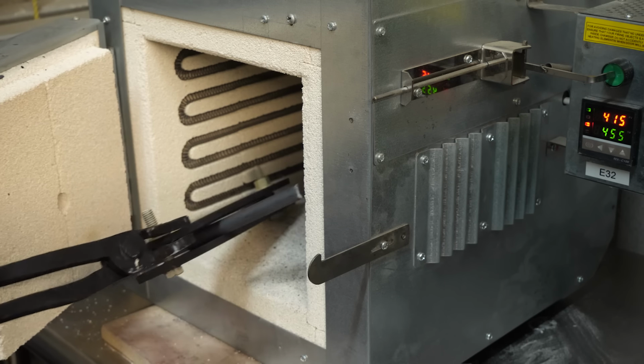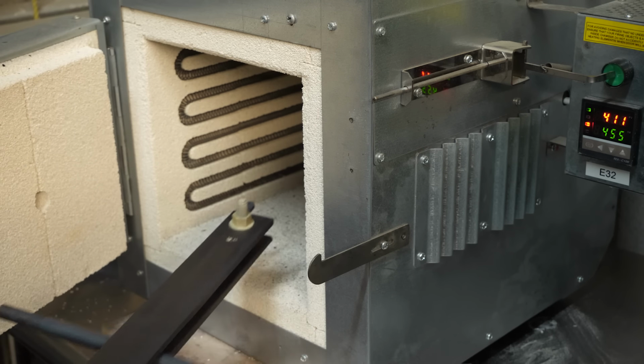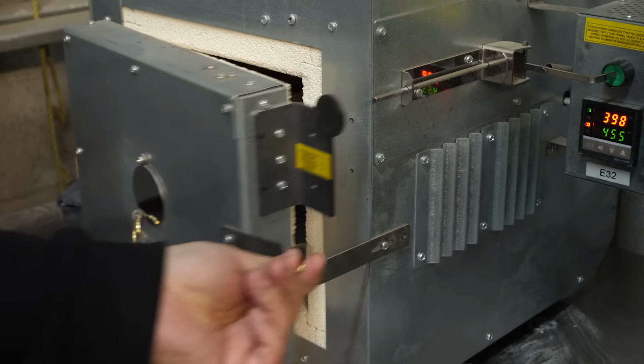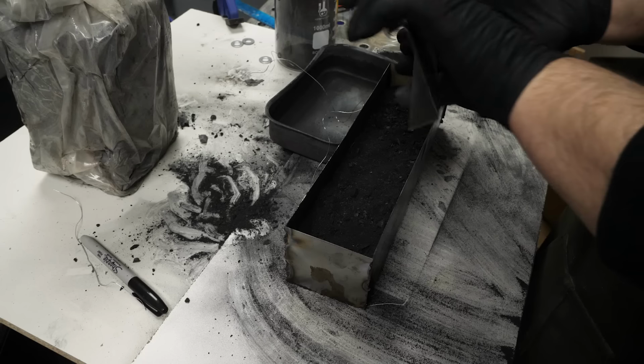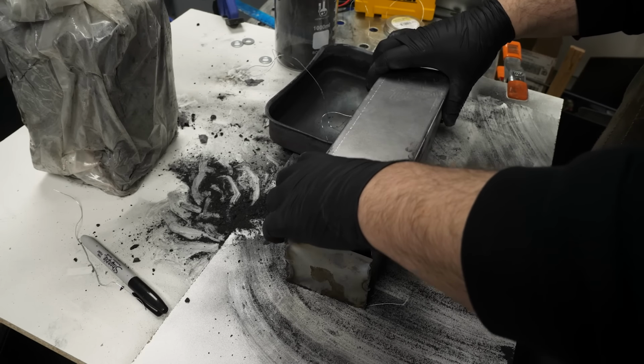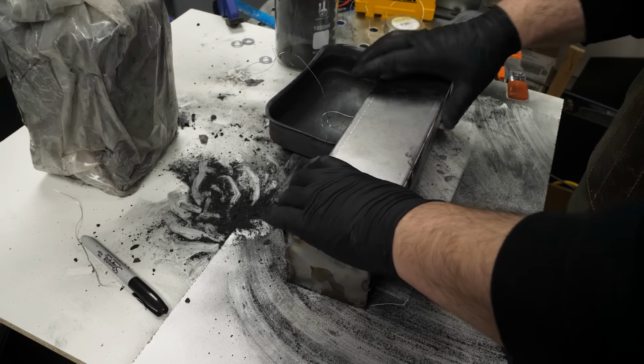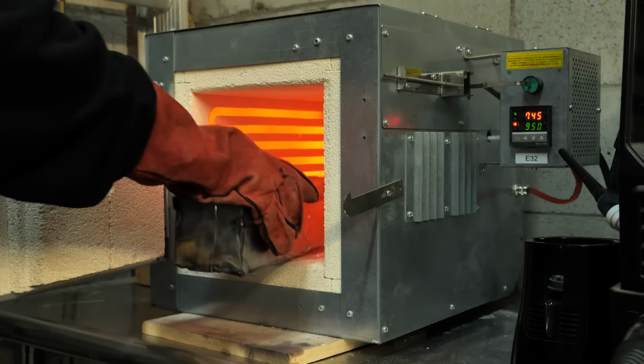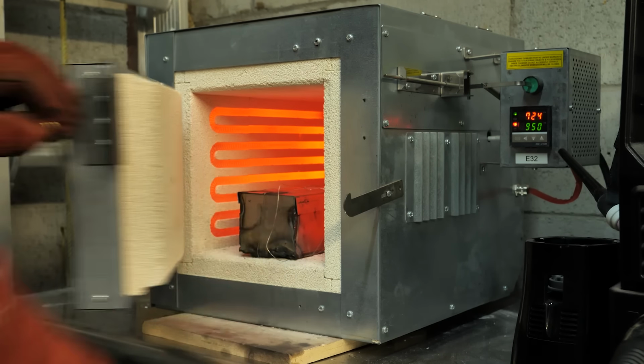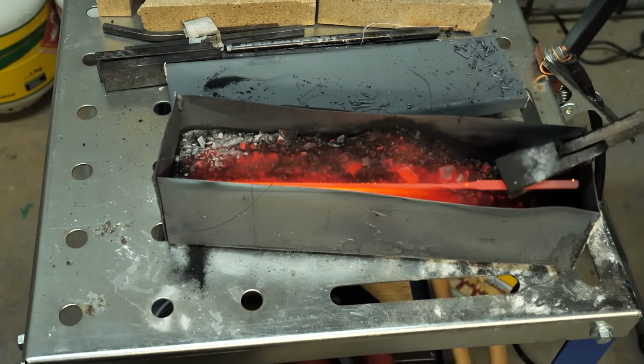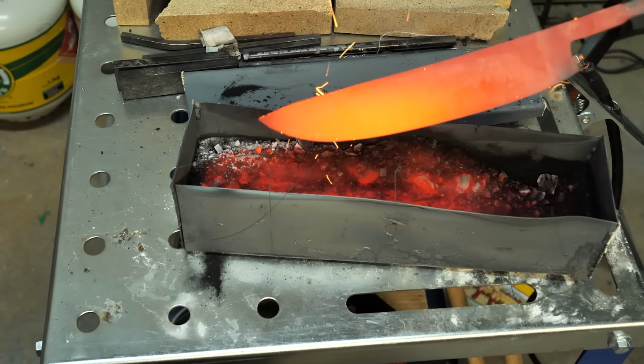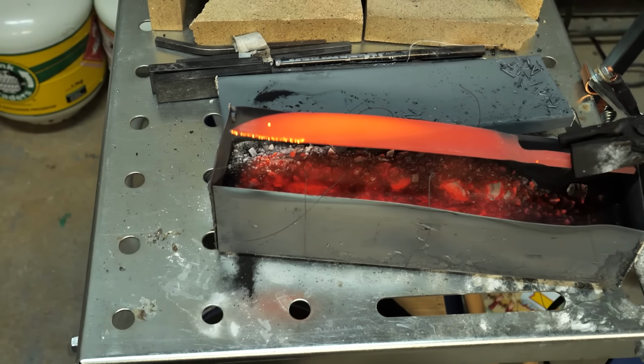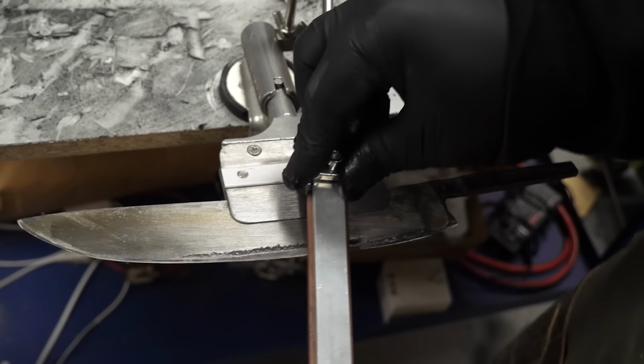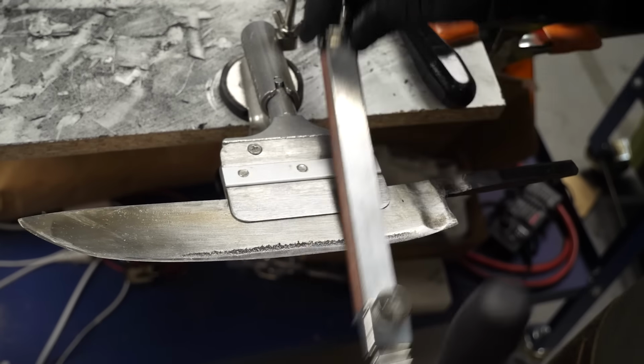Turns out we really ought to have cooked that initial piece longer, because the blade came out dead soft after tempering, which is not ideal. So guess it's time for more case hardening. This time I had to weld up a quick and dirty box to fit the knife, and we cooked it for an hour to make sure that there was plenty of carbon deep into the blade. And when that was done, it had to get heated again, re-quenched, and re-tempered before I could finally do the finishing steps. But while I put a nice edge on this and a handle, why does any of this actually work? What's happening to the steel as it goes from soft to hard?